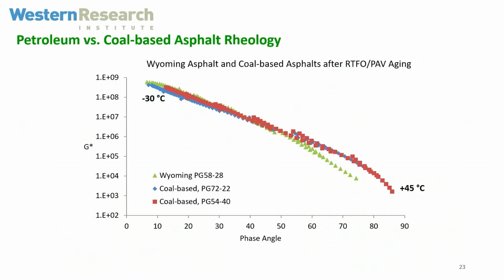So this one is, I guess, a bit technical, but this is looking at the rheology of these materials. So what I did is I took a typical Wyoming asphalt binder and compared this to those two products that we have, a low temperature asphalt and a higher temperature asphalt. And we looked at the rheology. So we're looking at how this material responds with temperature as far as how viscous it is or how elastic it is. And so we sweep this over all kinds of temperature ranges. So this data is going from -30 up to +45.